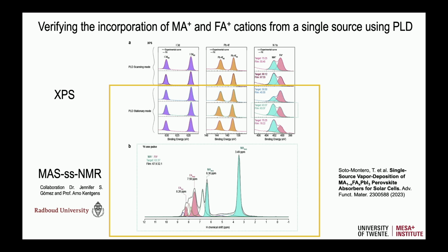So that's another example of a collaboration. We went to Radboud University, Professor Arno Kentgens, and then we basically had to make very thick films, scratch them, and measure the NMR. But we managed to do that, and you can see here one example of the NMR spectra, where we confirm that we have a good ratio of FA and MA. So we can say now, okay, we do this by PLD, because it was the first time we do MA-FA by PLD. I think nobody else did it before. This was a very critical measurement to confirm we had the molecules there, the perovskite forms, and we can quantify the amount of FA we had in the bulk.